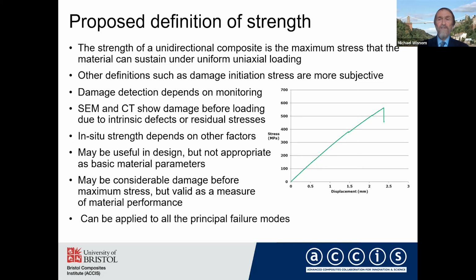And in fact, possibly even before you've applied any load due to intrinsic defects or residual stresses. So-called intrinsic in situ strengths are even more problematic in my view because they depend on many other factors, as I'll perhaps highlight a few of them a bit later. So these different definitions may be useful in design, they may be useful for certain particular purposes, but if we're trying to get to the bottom of the basic material parameter, then I don't think that's really what we should